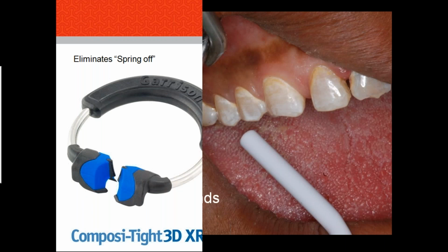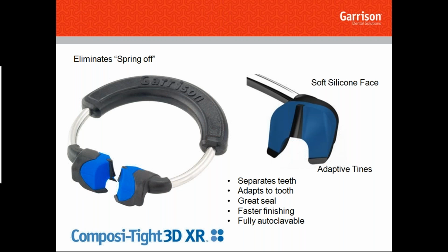So we're going to air dry for 10 seconds, and this is where we're going to employ the use of, we showed you before, the 3D ring. There's also the Composi-Tight, this Garrison product, the 3D XR, which is even more taut. It's got this beautiful silicone interface and this little nylon interdental extension there, which allows a really sound and very, very strong compression onto that tooth, and with our matrix allows us a beautiful opportunity to get the really enviable interproximal contact.